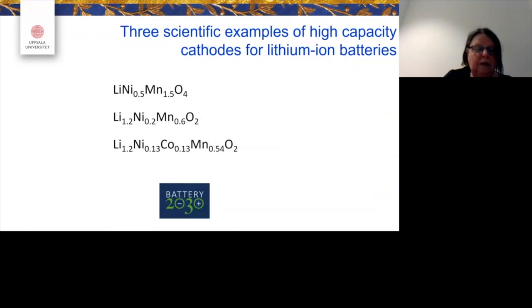And the three scientific cases I will browse through with you now are compounds that might look rather similar. These are hopefully future types of cathode materials that can give you higher energy content in a lithium battery. It's nickel manganese oxide, it's a lithium-rich manganese oxide, and it's a lithium-rich manganese oxide also containing some cobalt. And you see that the main component here is manganese. This is not the case for the commercial batteries coming out today. They have nickel as the main component. And if you go earlier in time, it was cobalt. The cobalt is something you want to get rid of.